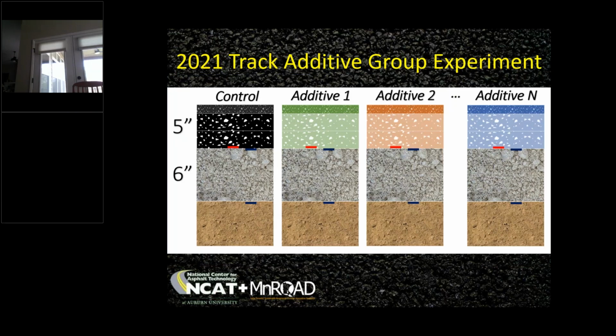Now, I wanted at this point to speak briefly about the additives. How do you account for the additives? We know what kind of a contribution we can get from the HiMA binder, the highly polymer modified binder, but we're doing an experiment on the next track that we'll build next summer, where we're going to build really thin pavements, 5-inch thick pavements, and we're going to use this experiment to come up with layer coefficients for the Kevlar fiber mix, or for epoxy mix, or for dry or wet process rubber mix.